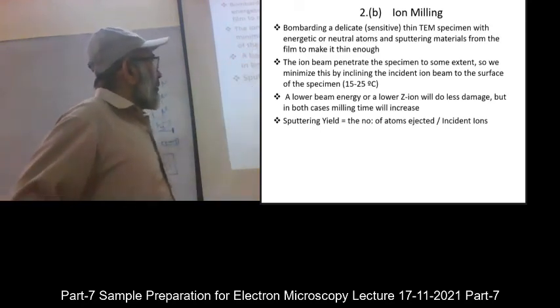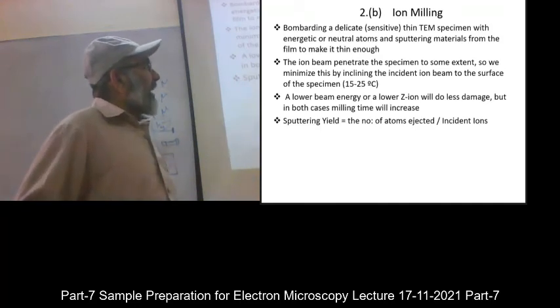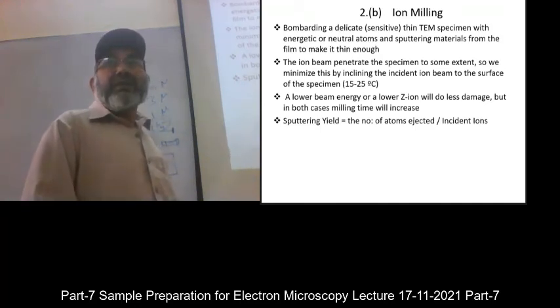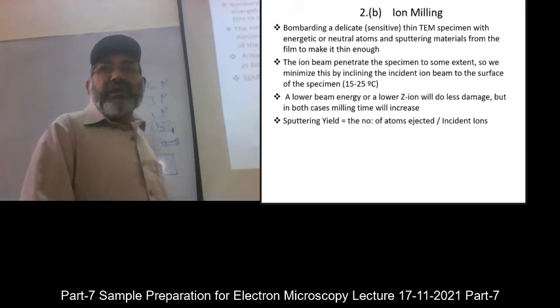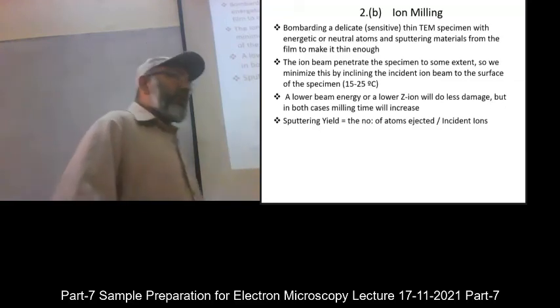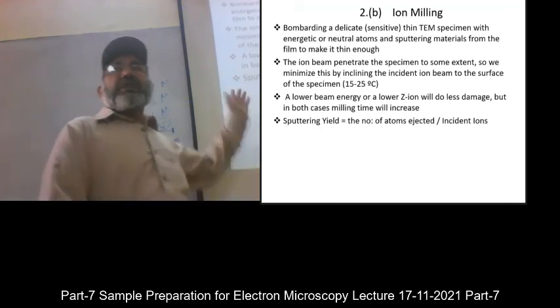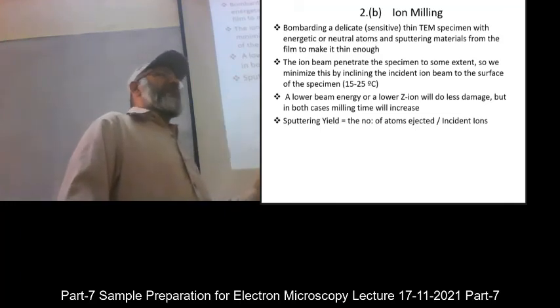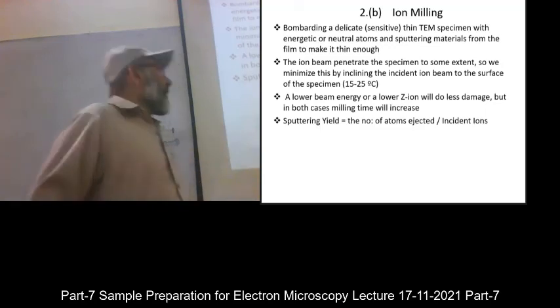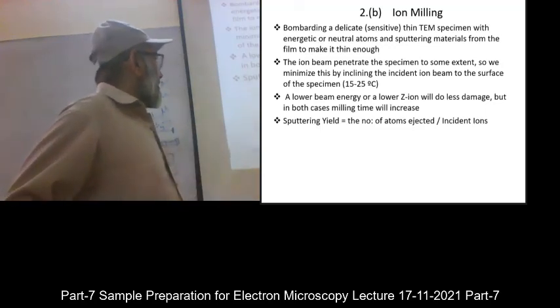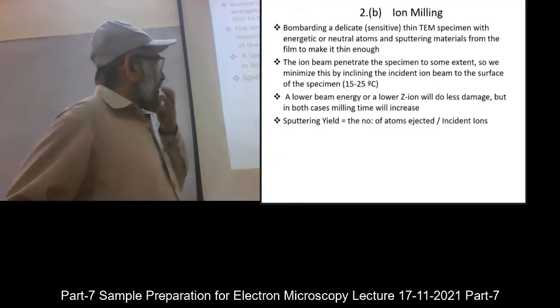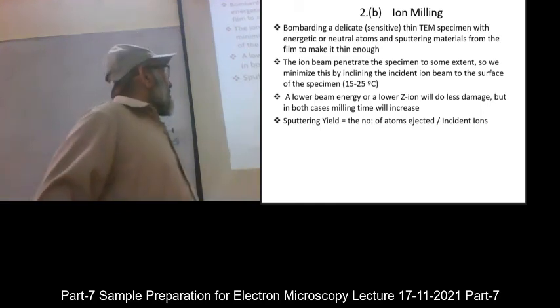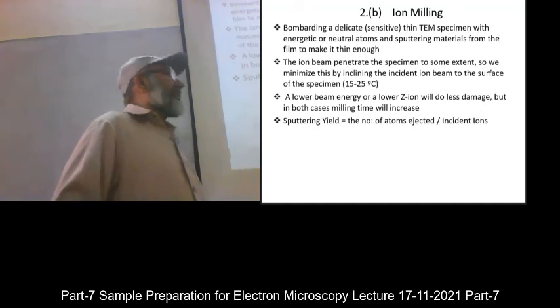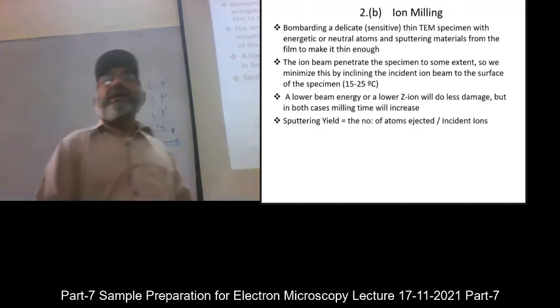A lower beam energy or a lower Z ion will do less damage. Z is atomic number, right? If a low atomic number material is used, then the damage will be much less in comparison to the high Z gases or materials which we use for ion thinning. Sputter yield is equal to the number of atoms ejected per incident ion. Number of atoms ejected and incident ions, right?